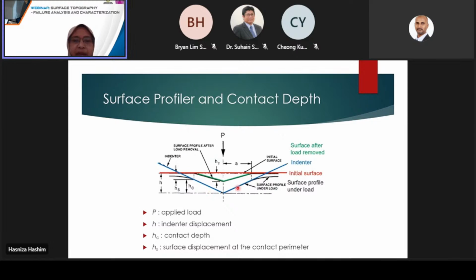This is the cross section of the indentation area. The initial surface of the sample before the tip approach is indicated by these red lines. The indenter profile is shown here as the blue lines. And the maximum depth that the tip reaches from the initial sample surface is considered the penetration depth, which sometimes we also call h or h max. So that would simply be the initial surface being near zero, and then wherever the tip reaches being the maximum depth.